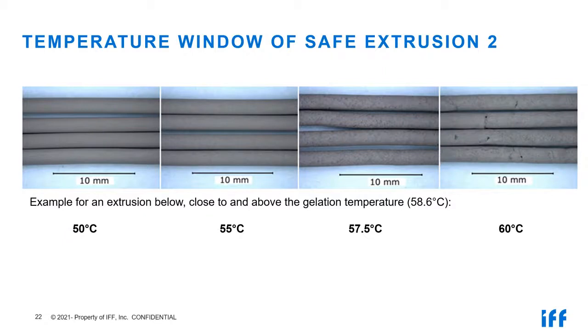Then picture number 3, very significant. You are still 1 degree below the gelation temperature, but you already get a very coarse and porous structure, deformation of the shape. It was a full profile, not a hollow profile. A hollow profile would look even worse, you can be sure. And smaller pores on the surface.